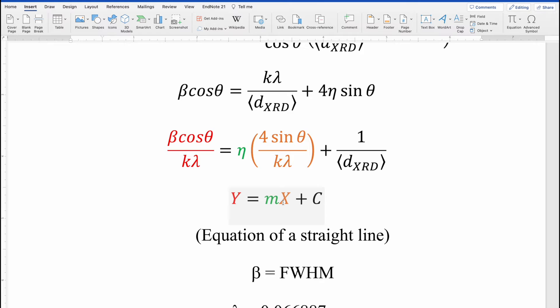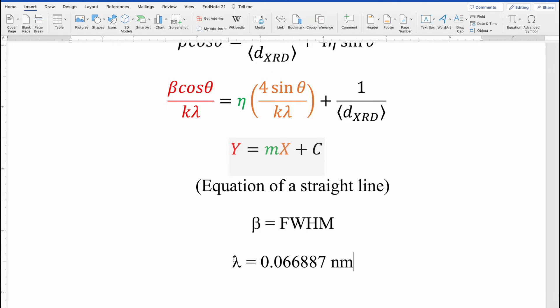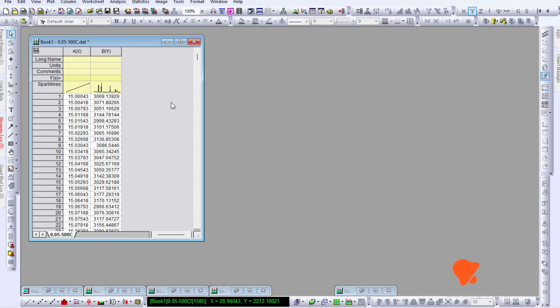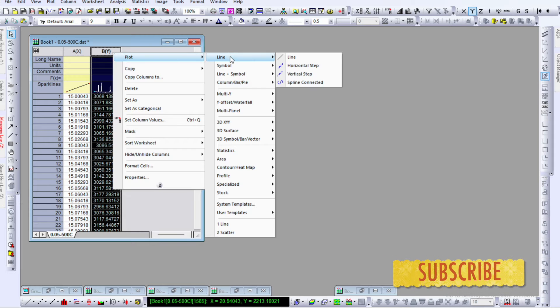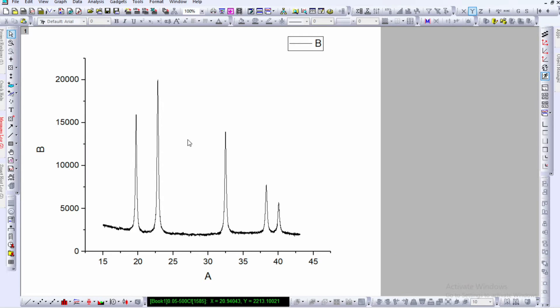If you plot and fit a straight line, the slope gives you m (the strain eta) and the y-intercept gives you c (equal to 1 over D_XRD). In this case I have used synchrotron XRD, which is why the wavelength looks very small. If you used copper K-alpha, the wavelength would be 0.154 nanometers. Open Origin software, drag your XRD data file, click on the column, right-click, go to Plot, then Line, to see the XRD diffractogram with 2-theta on the x-axis and intensity on the y-axis.